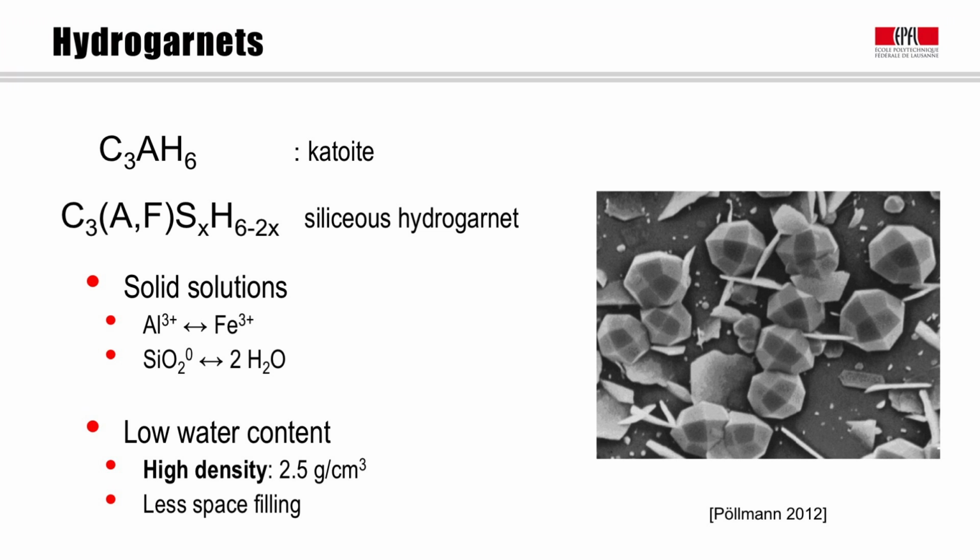And in this case, this is actually the phase where most of the iron goes to in Portland cement paste. So I said that the iron, because of its low mobility in high alkali solutions, doesn't go much into the ettringite, doesn't go much into the AFm phase, but it does form these siliceous hydrogarnets, which there ends up being quite a lot of, but it's rather poorly crystalline, so not often well detected by XRD.